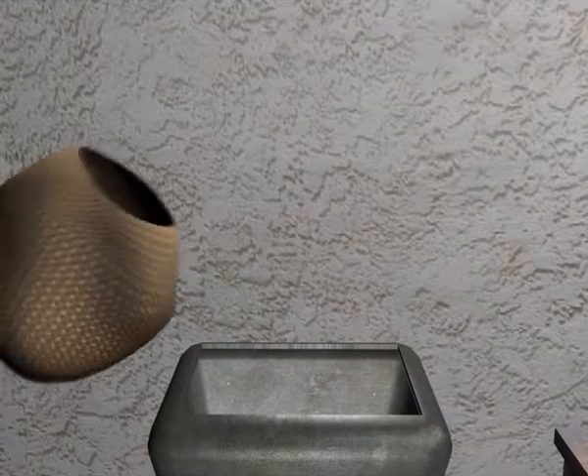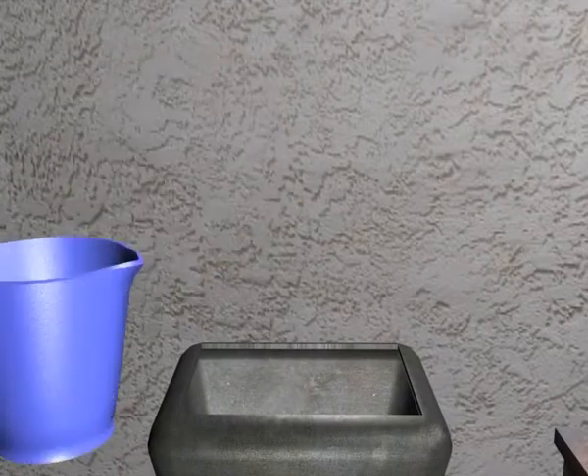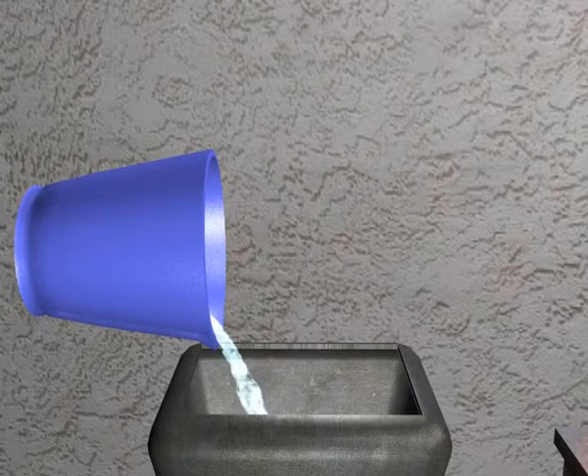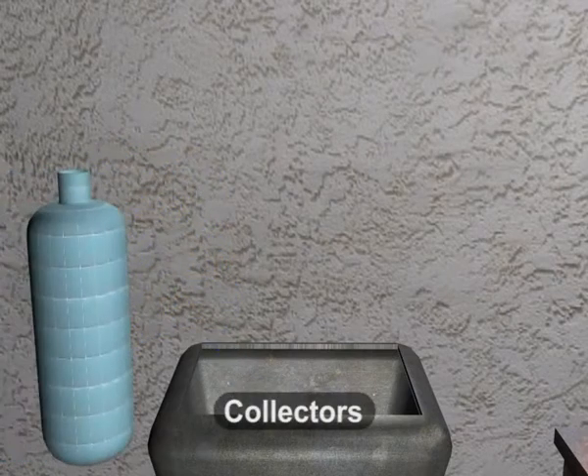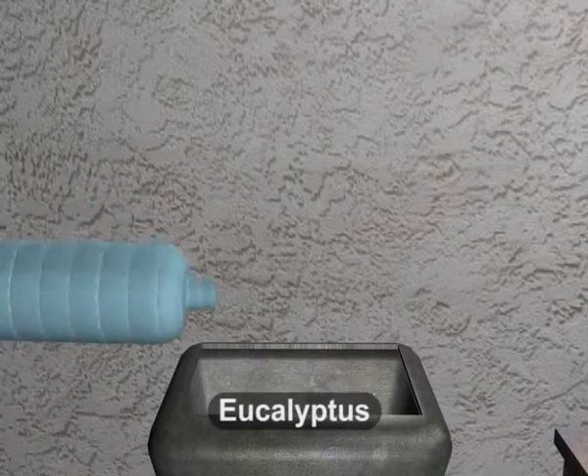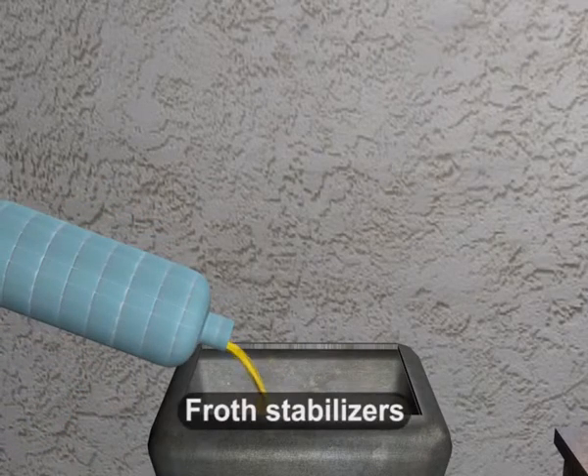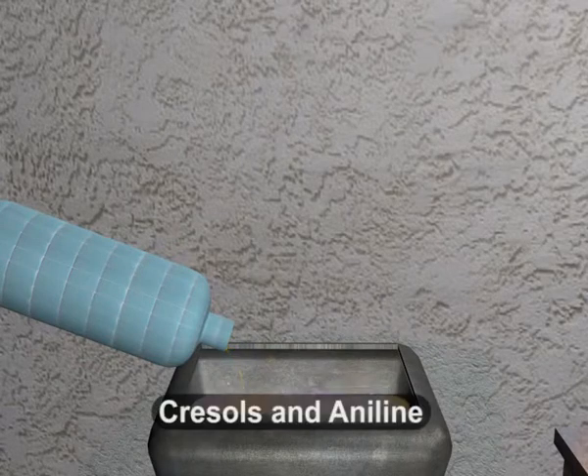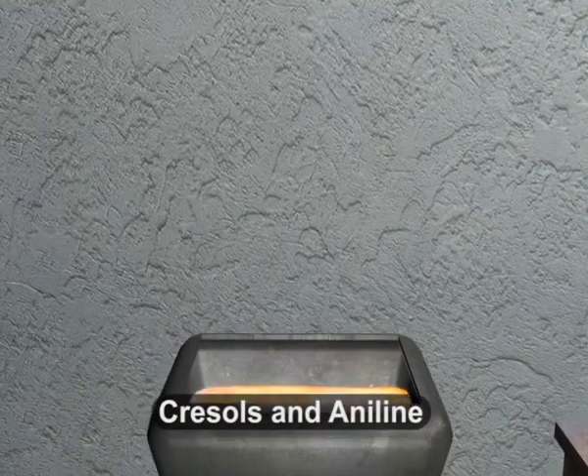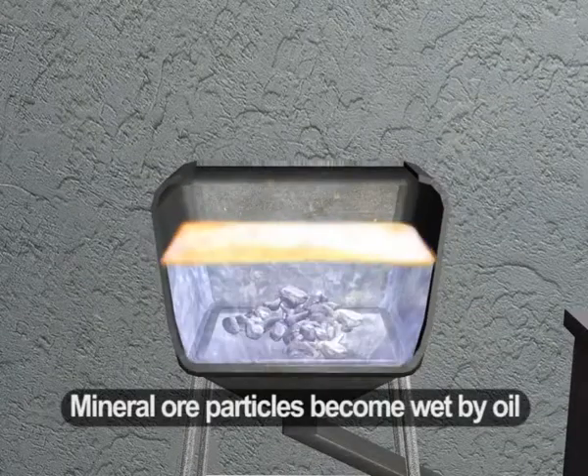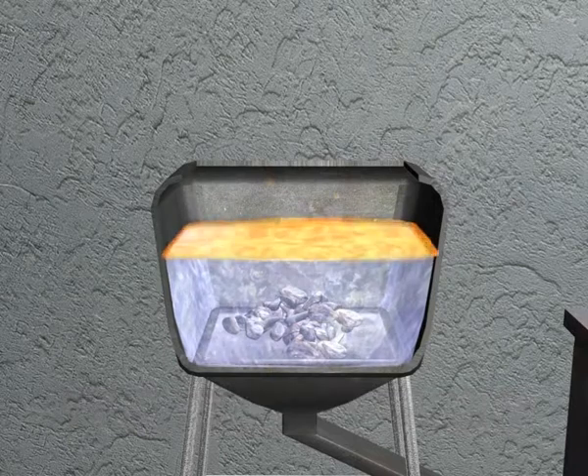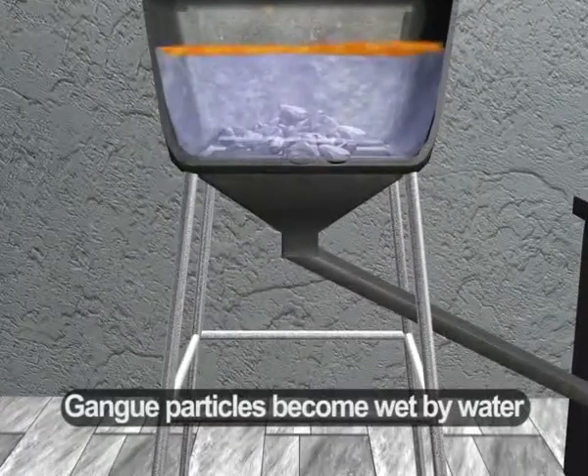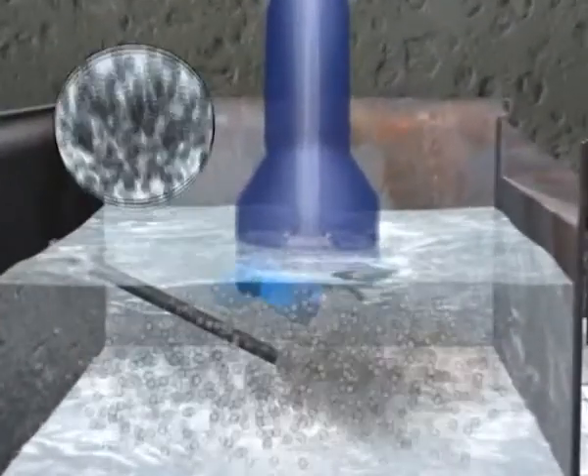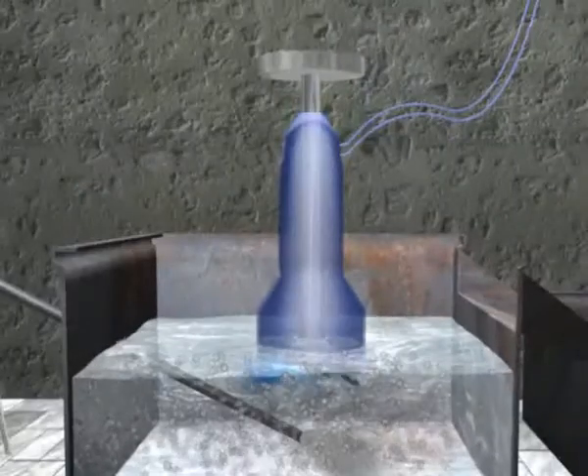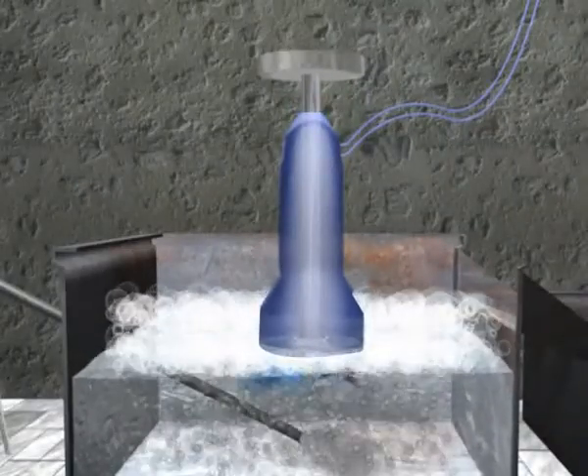In this method, the powdered ore is mixed with water to form a suspension in a tank. Small quantities of collectors such as pine oil or eucalyptus oil and froth stabilizers such as cresols and aniline are added to the suspension. The mineral ore particles become wet by oil, whereas the gangue particles become wet by water. The water is agitated by a rotating paddle or by blowing air violently. As a result, the froth is formed.